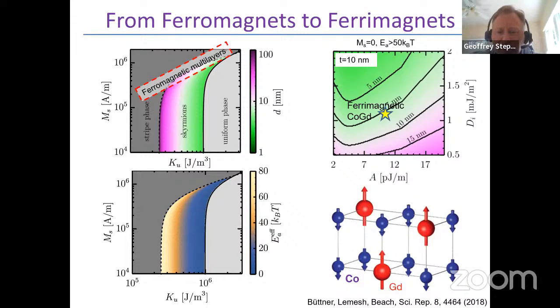In these kinds of materials, you can reduce and even eliminate stray fields, which allows you to make the film much thicker. But by virtue of making the film much thicker, the energy that protects a skyrmion from annihilation is really a volume energy. And so if you want to make a skyrmion smaller in diameter, so smaller in the plane, in order to imbue it with enough energy to protect it against collapse, you desire to make the film thicker. So the smaller the skyrmion is, the thicker the film needs to be, so that the volume energy that stabilizes that skyrmion is enough to fight the thermal energy.